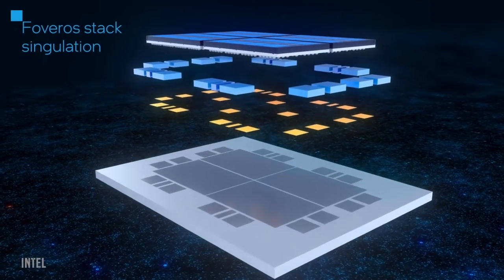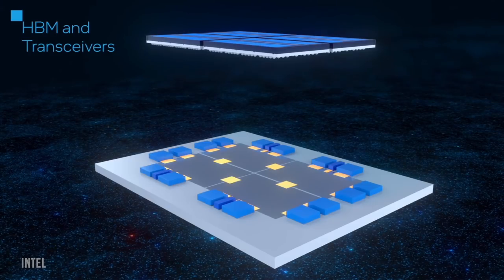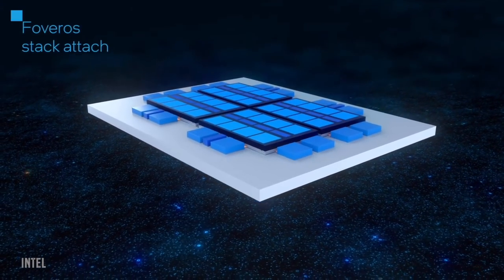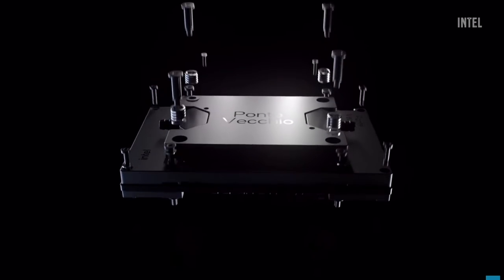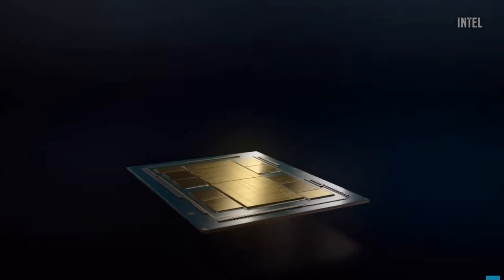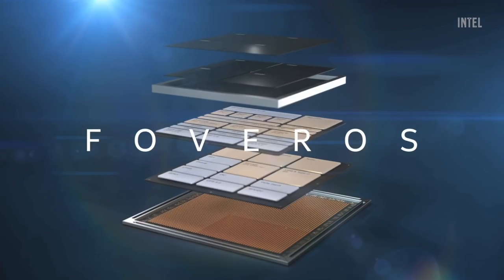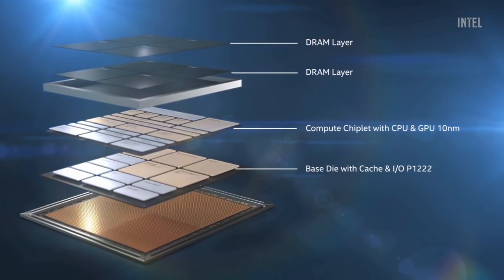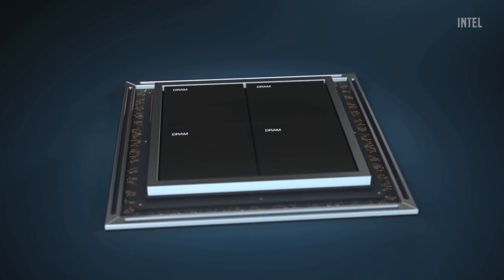Tiles are interconnected using Intel's EMIB — Embedded Multi-die Interconnect Bridge technology — essentially micro bumps at much higher density than on a standard packaging substrate. Micro bumps are tiny balls of solder forming a high-density bridge connecting one tile to another, allowing them to communicate and share resources. This enables increasing core counts, cache size, memory, and I/O. For vertical stacking of chiplets, Intel introduced Foveros — logic-on-logic die stacking — used first for the Lakefield chip. This integration allows extremely high bandwidth between the two chiplets, though the dies must be co-designed and floorplanned together to manage power delivery.